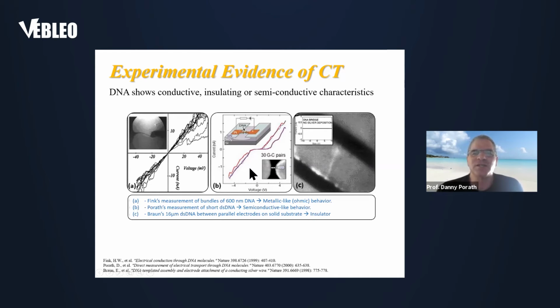This resulted in my postdoc work with Cees Dekker at Delft. In this experiment, we decided to measure short, 10 nanometer, 30 base pair long DNA molecules, all homogeneous, poly G, poly C, and we trapped them between two electrodes in the scheme that is shown here. We could show, with the help of a lot of controls, that a current could flow through the DNA between the electrodes. But the drawback in this experiment was that we could not see the molecule. It was very hard to verify that there is indeed just one molecule, and we had to use a lot of additional controls in order to do that.